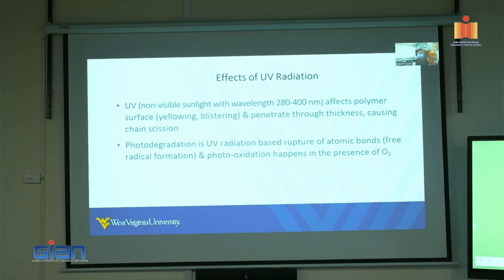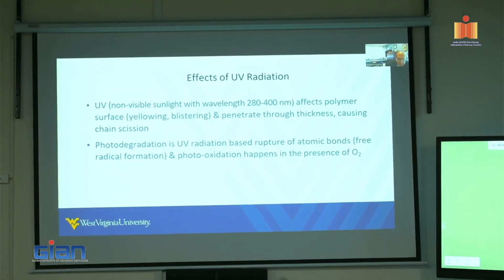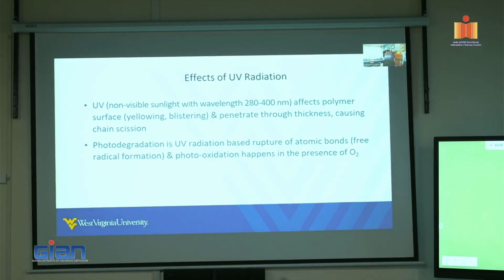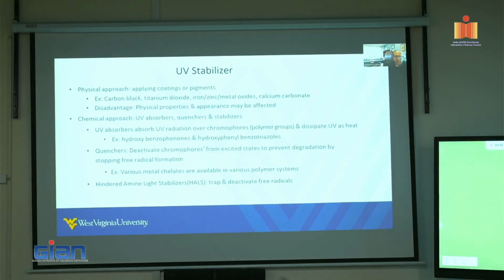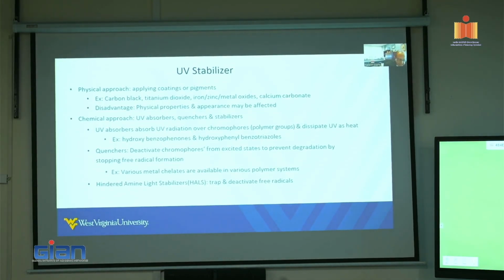Once free radicals are formed due to the absorption of UV light in the polymer, these free radicals can react with oxygen if it is present, giving rise to peroxides. Peroxides cause chain scission and a reduction in mechanical properties. To minimize this effect, one uses UV stabilizers, and the approach could either be physical or chemical. One can put in additives like carbon black or titanium dioxide, or put in UV absorbers, quenchers, and stabilizers, and there's a wide variety of these materials available, and some of these are listed on this.